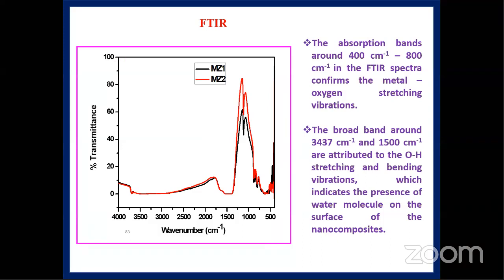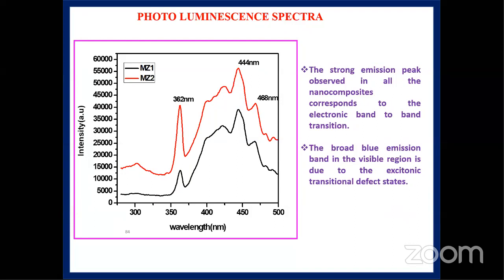And then we performed FTIR. The absorption band around 400 to 800 centimeter inverse confirms the metal oxygen vibrations, like magnesium-oxygen and zinc-oxygen. The broad bands around 3437 centimeter inverse and 1500 centimeter inverse are attributed to the OH stretching and bending vibrations, which indicate the presence of water molecules on the surface of the nanocomposite. And then we performed photoluminescence. You can see the graph, with a strong emission peak at 444 nanometer observed in all the different ratios of this nanocomposite, due to the band to band transition. And also the broad blue emission band in the visible region is due to excited transitions from defect states.